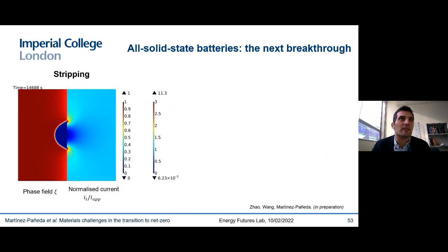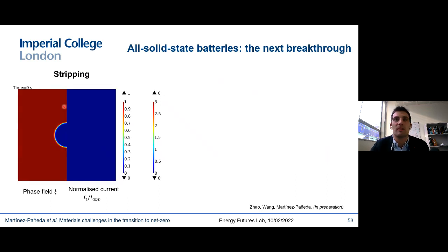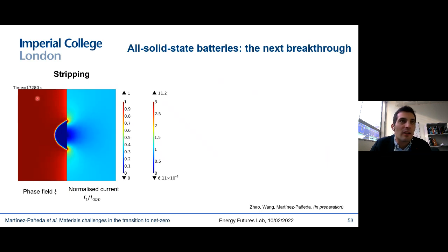So let me show you some representative results. You can see here how a single void behaves under stripping. As expected, the void enlarges along the interface. This is what you see in the experiments. And you can see here, on the left I'm plotting the phase field, so blue is the void and then red is the lithium metal. And on the right I'm plotting the distribution of current density. And you can see how those hotspots form near the void edges and how they sort of enlarge as we go along with the voiding process.